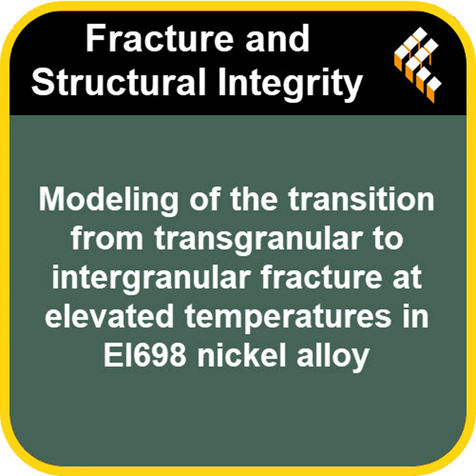Precisely. And they back this up experimentally. That critical energy release rate, GC, was determined in two distinct ways. First, they looked at energy dissipated during cyclic loading tests on samples that already had a crack. They measured the area inside the hysteresis loops on the stress strain graphs. That area represents energy lost per cycle, which relates to crack growth. Second, they correlated GC with the critical strain energy density, measured in tests on smooth, uncracked cylindrical specimens. Basically, how much energy the material could absorb right up to the point of failure. Two different ways to measure the same property.